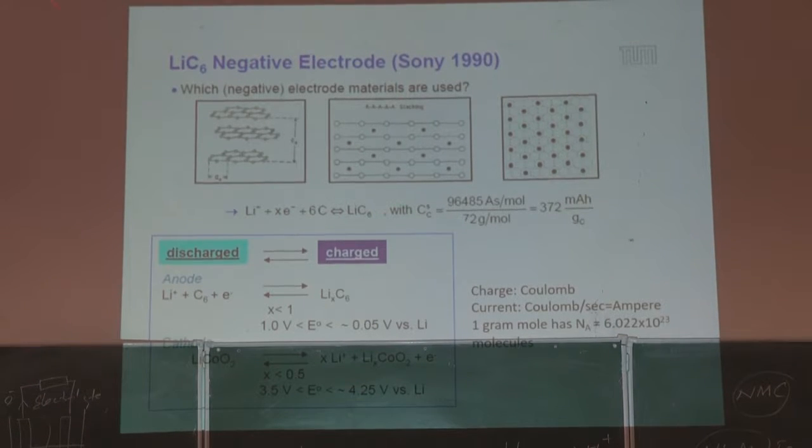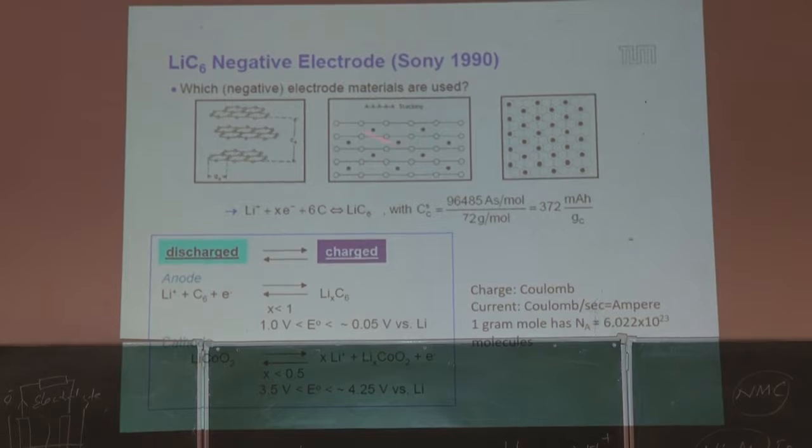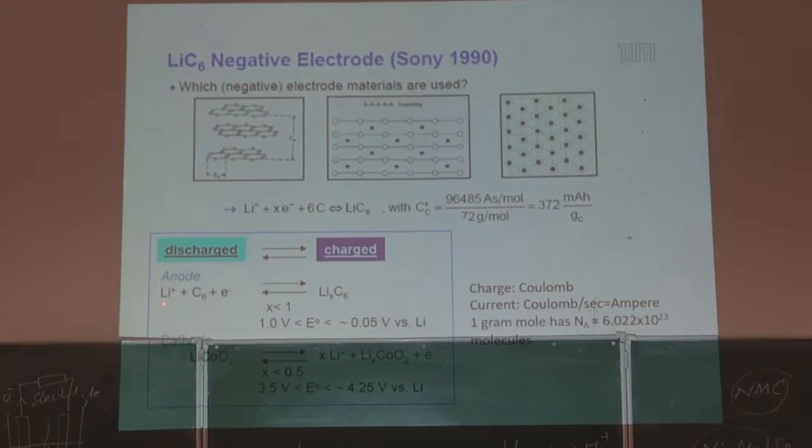So this shows you how to calculate. I think everybody has a homework. You can do this one. When lithium intercalates in graphite, eventually it makes LiC6. This means for 6 carbon atoms you get 1 lithium atom. So from this you can calculate what is your charge capacity, right? You know the atomic number. So carbon has 12, right? Then we know the Faraday constant, because that involves the electric charge and the Avogadro number. If you calculate that, it comes to 370. That's very easy to calculate.